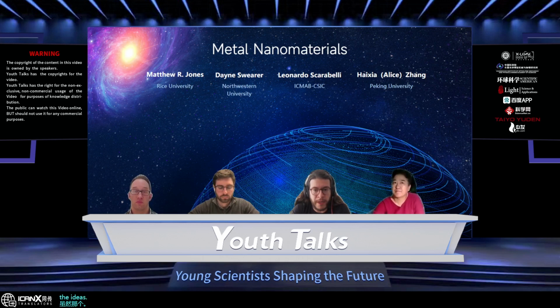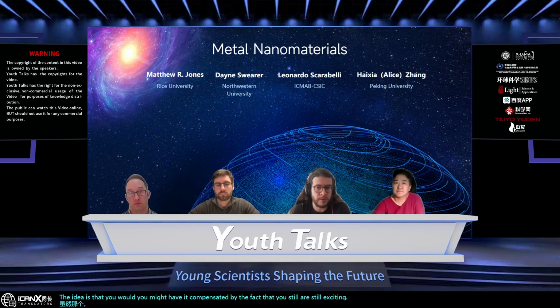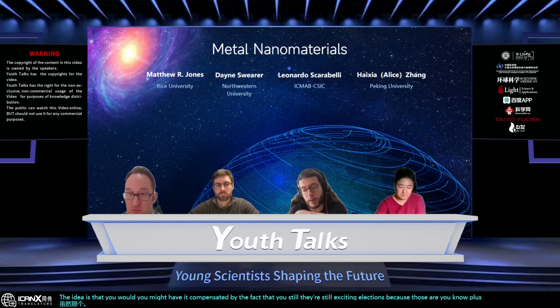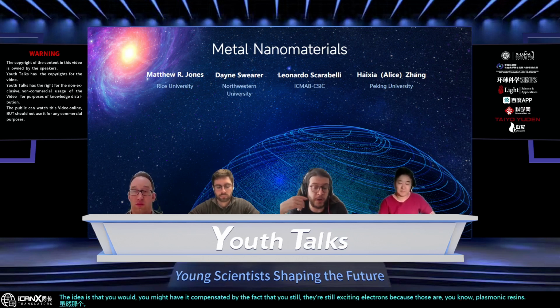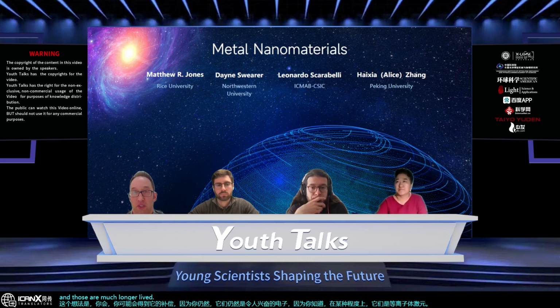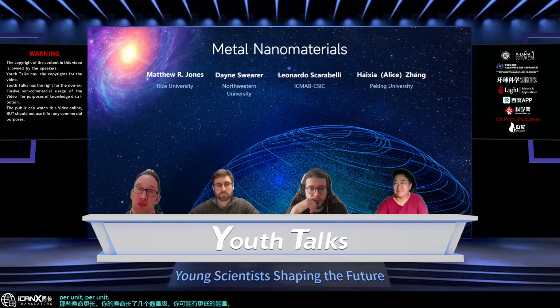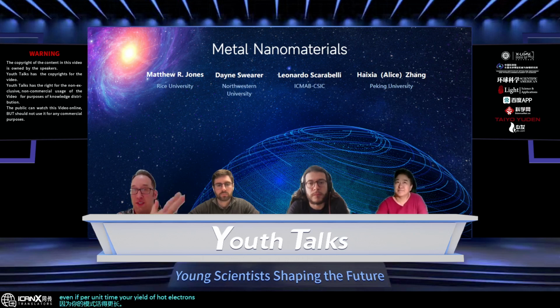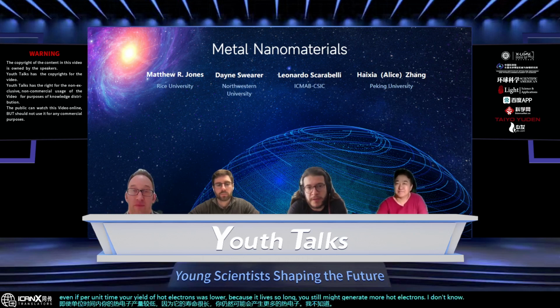Though the idea is that you might have it compensated by the fact that you're still exciting the electrons, because those are plasmonic resonances anyway in a way, and those are much longer lived. Your lifetime is orders of magnitude longer. So maybe lower energy per unit, but per unit time your yield, because your mode lives for so much longer. Even if per unit time your yield of hot electrons was lower, because it lives so long, you still might generate more hot electrons. I don't know. Correct. That's the bet, at least.